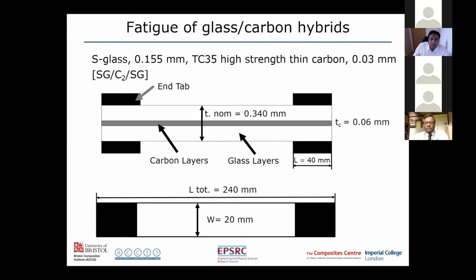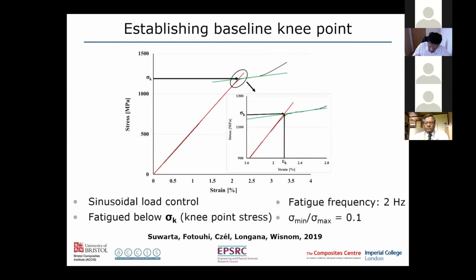We've also done work on looking at the fatigue performance, which is actually pretty good. In this case, it's another different fibre, but a similar high strength thin carbon sandwiched between glass. So the first thing is we established the baseline knee point. We have this nonlinear stress strain response. We establish that knee point, and then we can fatigue it at a level below that knee point and see how it performs. Those fatigue tests were done in sinusoidal load control at 2 Hertz with an R ratio of minimum to maximum stress of 0.1.